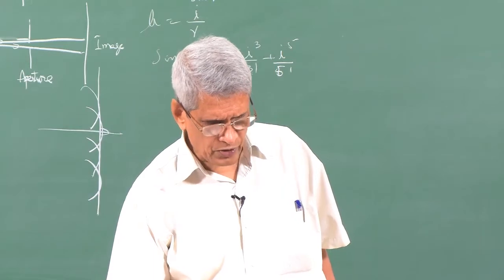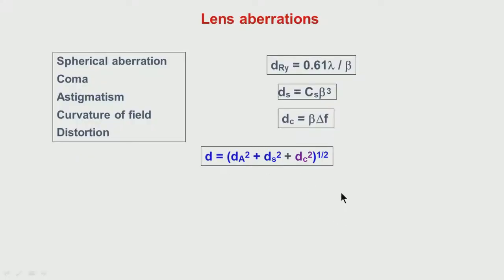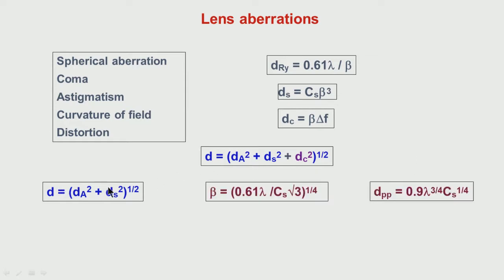Then these two are the ones which are essentially going to decide the aberration, decide the resolution. Okay, we can write it like this, substitute these values. But if you look at the variation, here it is inverse of beta, here it is beta cube. So we can optimize it and find out for what value of beta we will get the best resolution. That we can obtain by differentiating, and then the beta value turns out to be 0.61 lambda by Cs root 3, the whole to the power of 1/4.